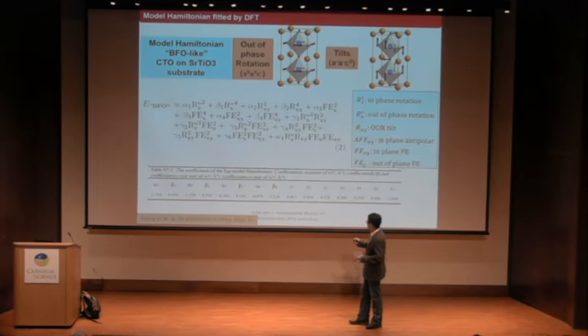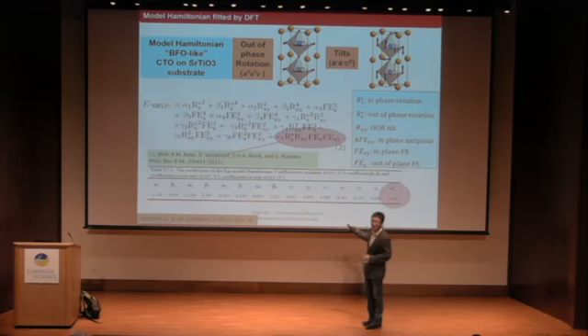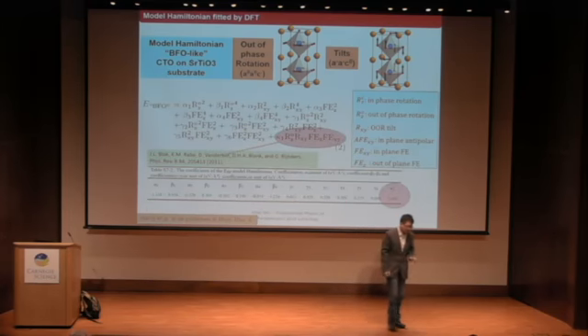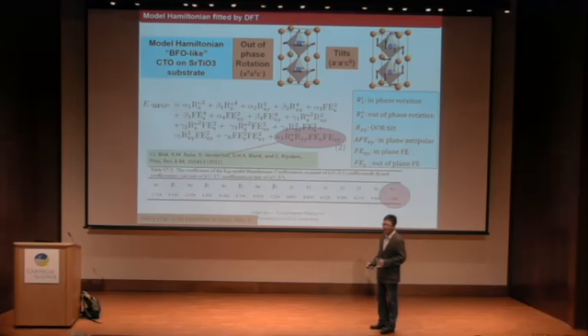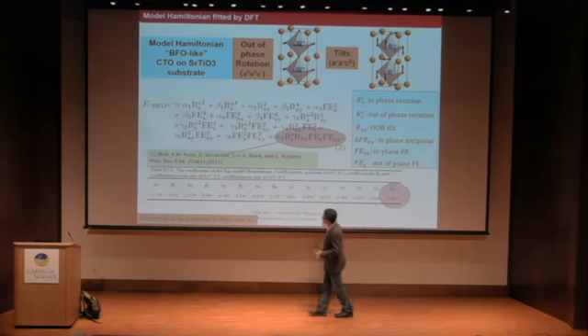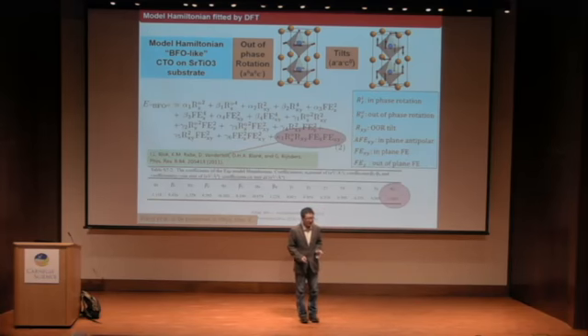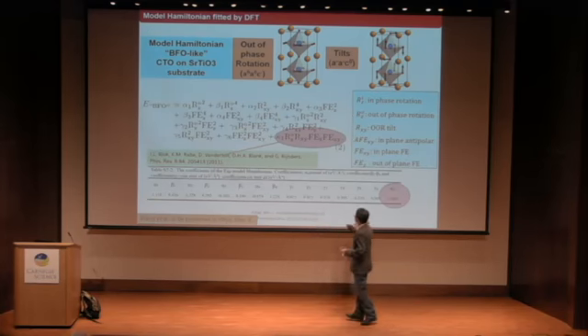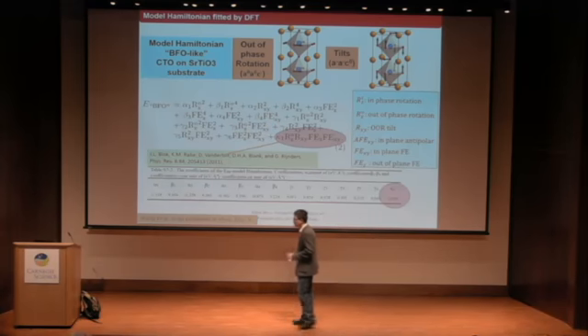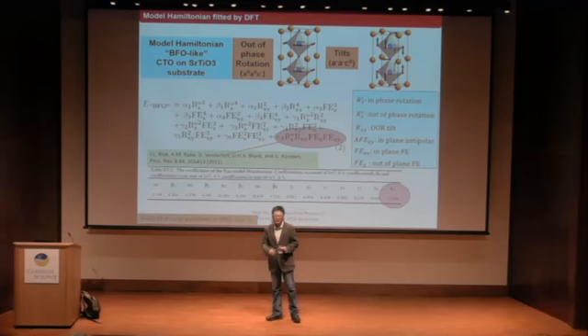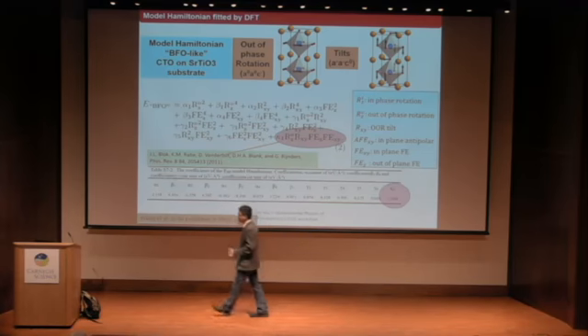Again, we see a large term in the end, which is a trilinear, full terms coupling term. We are not the first to realize this trilinear coupling term - it was realized by David and Karin in a paper several years ago. There is a corresponding large negative coefficient, meaning that if this happens, the energy will be lowered significantly.